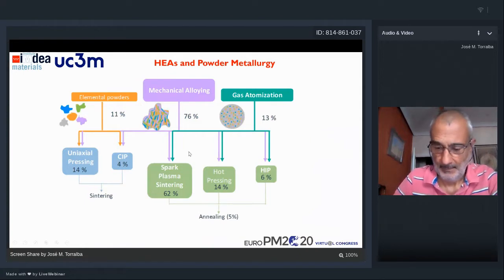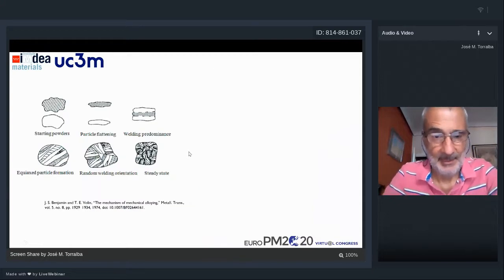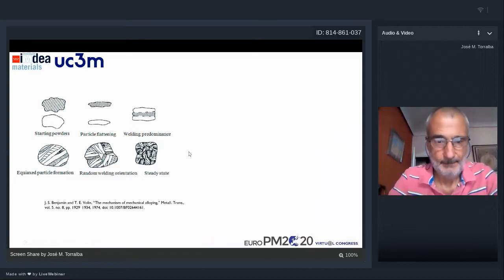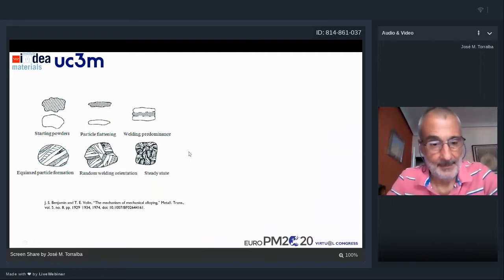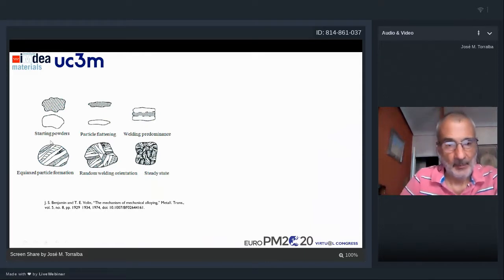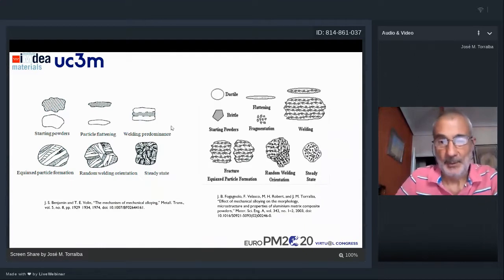sintering. It's interesting to analyze the mechanical alloying process in high entropy alloys. If we are using just metals, we expect, in principle, a behavior that was described by Benjamin many years ago, in which we have an evolution of the powders in the so-called ductile mechanism, in which we have the starting powders, a flattening of the particles, welding, fracture, and then welding again, and then we reach the steady state. On the opposite side, we have the so-called brittle-ductile mechanism, when you have brittle particles and ductile particles, and the evolution of the final particles follows these different steps.